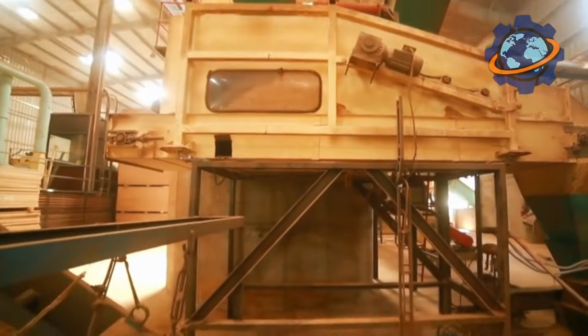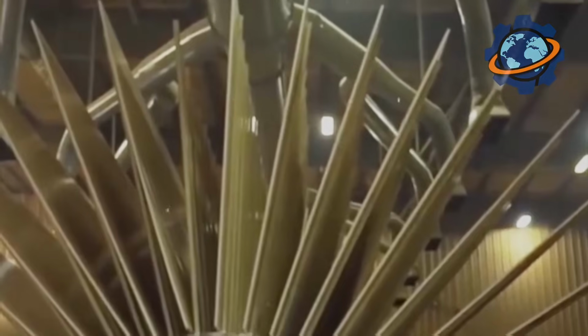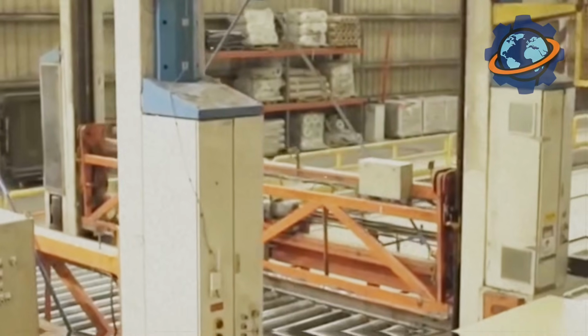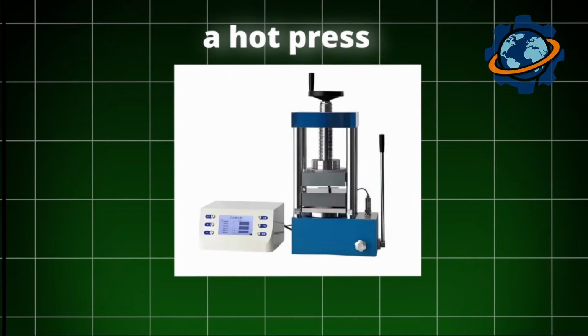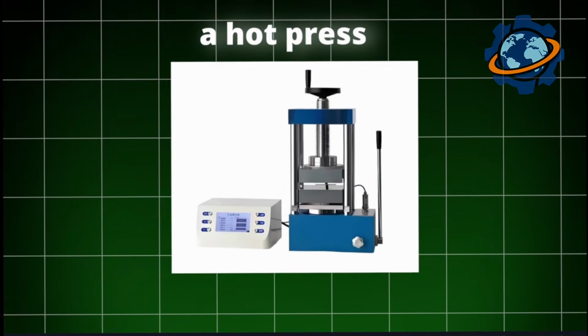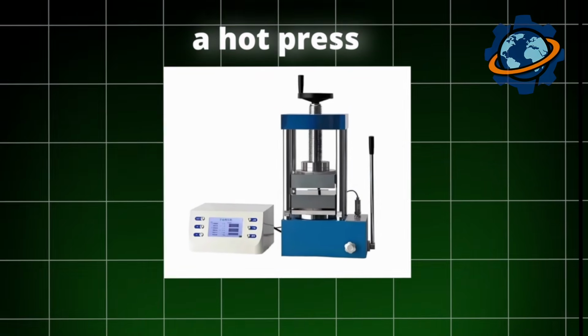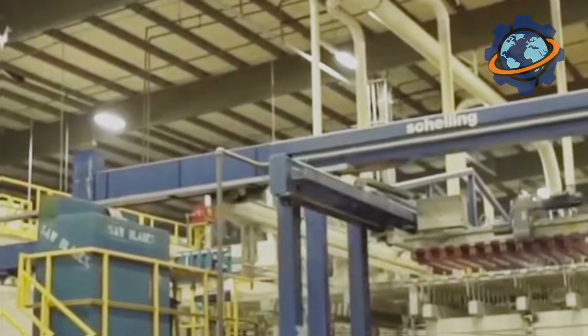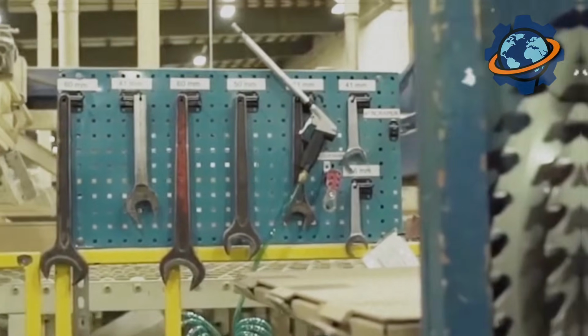It activates the resin, causing it to polymerize and permanently glue the fibers into a single solid block. And at the same time, it evaporates any remaining moisture, which escapes from the board as hissing steam. After a few minutes in this steel embrace, the fluffy mat transforms into a hard, dense, perfectly flat, and still very hot board of medium-density fiberboard.